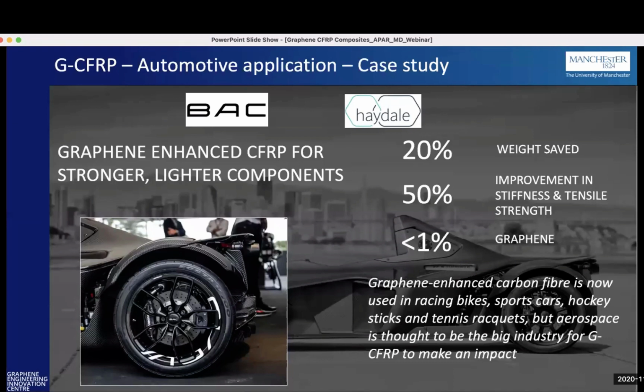From that, they also designed new components. They designed a component prepreg which used less than 1% graphene in its resin system. From that, they increased stiffness and tensile strength by approximately 50%, which in turn allowed them to use less material in their parts, saving around 20% of the total car weight. And if you think that the car itself only weighed 600 kilos to start with, that's quite a saving. It also enables their customers to drive around a track a lot quicker than they would normally.